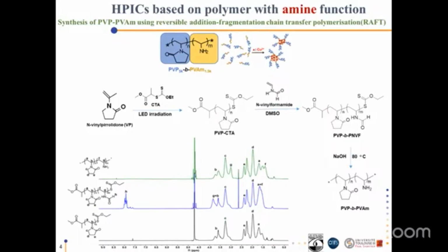It's necessary to say that polyvinylamine is a water-soluble polymer with a high content of primary amine groups, which easily complex with metal ions. So the use of polyvinylamine instead of the more commonly used polyacrylic acid is expected to enhance interactions with copper ions. The PVP-PVA block copolymer was obtained using RAFT techniques. You can see a scheme in the picture. In the first step, a PVP macro chain transfer agent, PVP-CTA, was prepared.